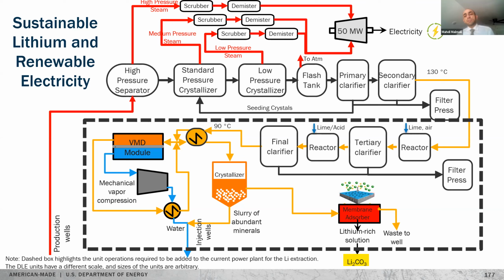clarifiers. In the first reactor, we will add lime and air to essentially knock out all the iron and silica. Essentially, we will reduce their concentrations to less than 5 ppm and then remove them in the clarifiers. After this, we believe the temperature of the brine is around 90 or 100 degrees C. Then we will send it to a heat integration process to make sure the heat is properly preserved. And then it goes to a vacuum membrane distillation module.